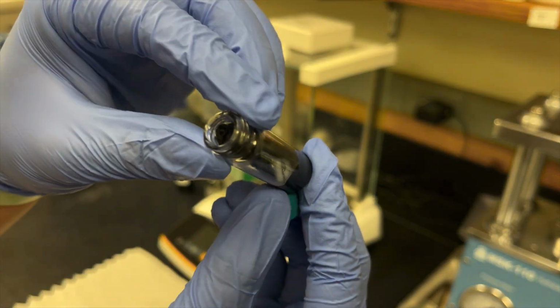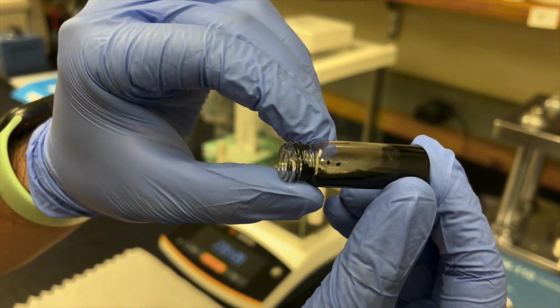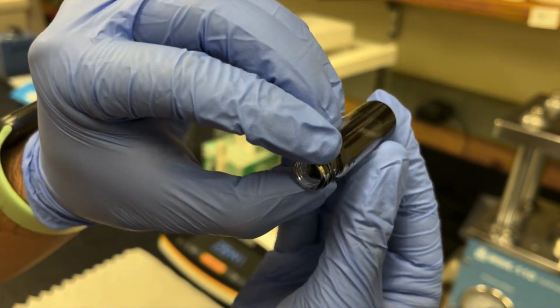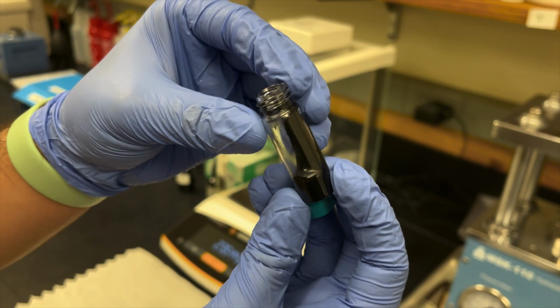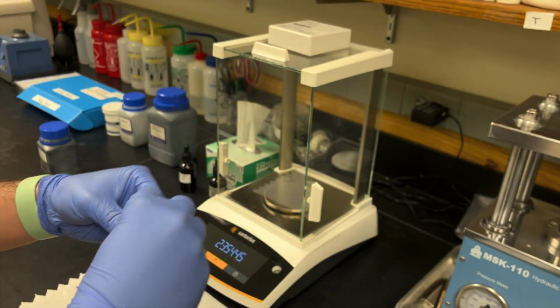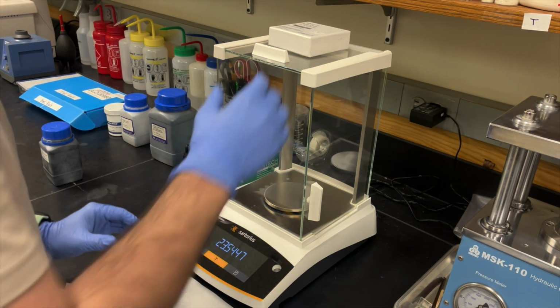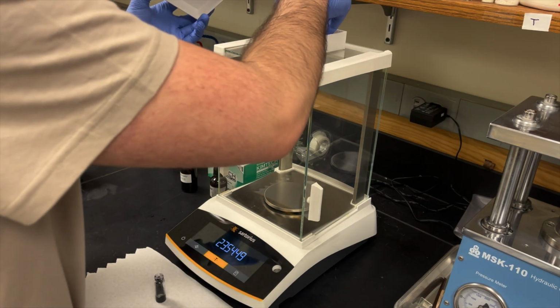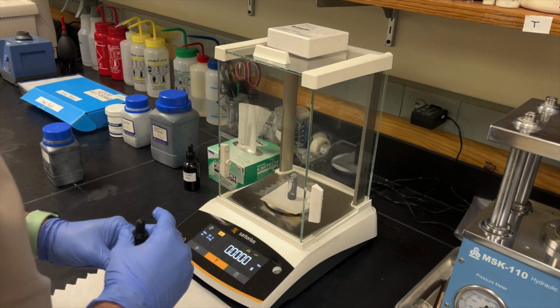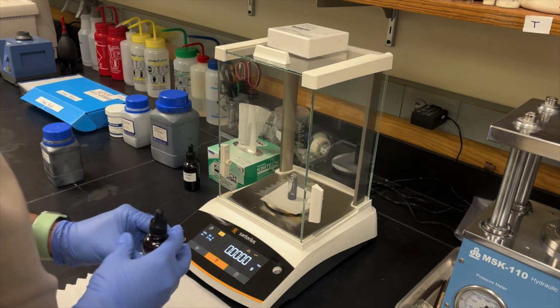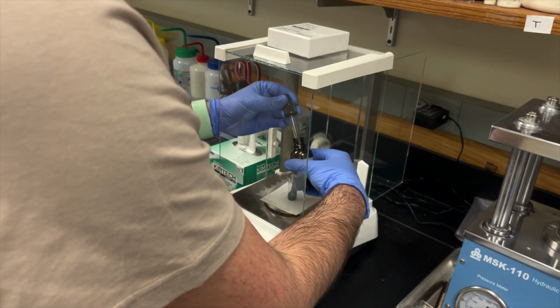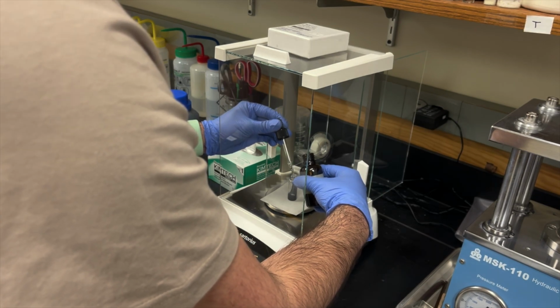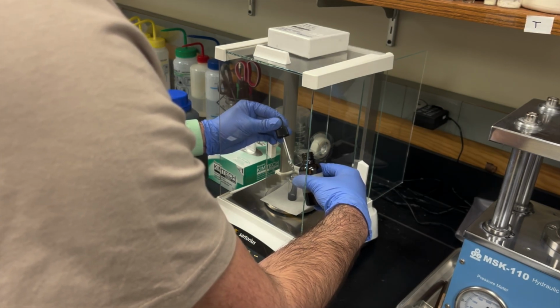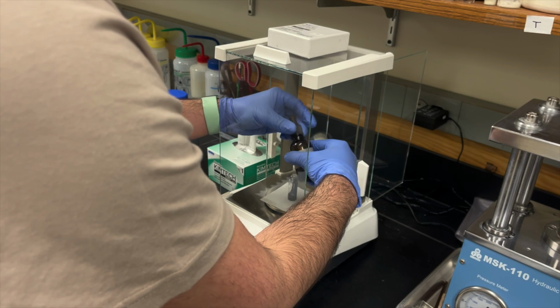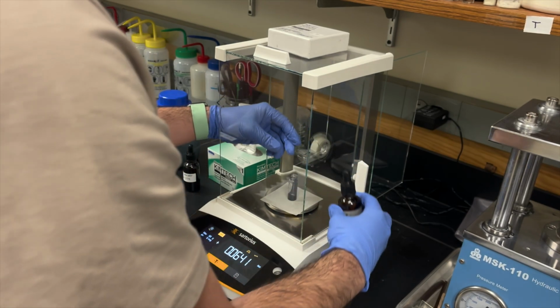Because of the heat that can sometimes arise from sonication, the slurry may become thicker. If this happens, we will then have to add more NMP so that we maintain the desired consistency post-sonication. For the sake of repeatability, we will want to take note of how much NMP is added both before and after sonication. This can be very helpful as you try to consistently recreate a particular recipe.